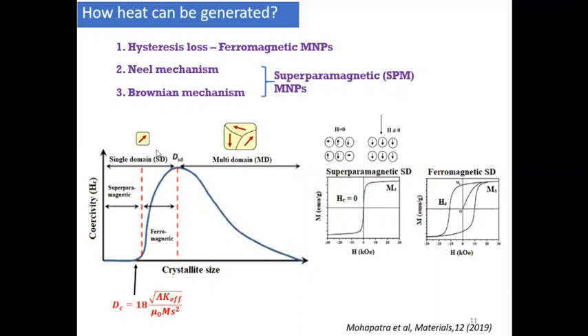Generally, if you take any ferromagnetic or ferrimagnetic material like iron oxide, which we are using here, it has a specific size, and below around 80 nanometers it shows the superparamagnetic region. Superparamagnetism is required, and the heat will be generated through the Neel mechanism or the Brownian mechanism.